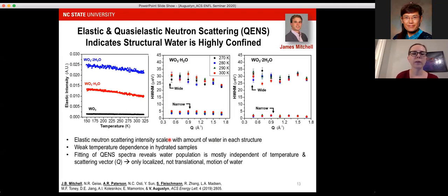We also found that when we looked at the quasi-elastic neutron scattering, so very small energy transfer between our sample and the neutrons, the water population was mostly independent of temperature and scattering vector. So what that meant was that the water that's confined in these layers has no translational motion. That's what we mean when we say highly confined. It has no translational motion.